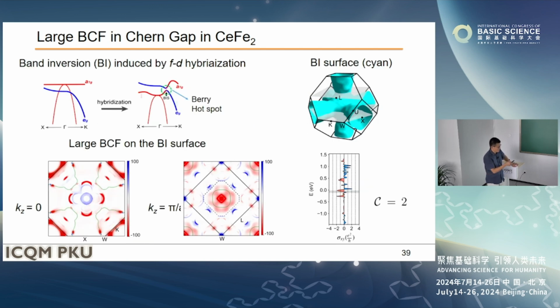How to understand it? So through the calculation, after the hybridization, you see this flat band hybridized with the f electron of cerium and open a small gap. This gap is a very strong curvature hotspot, and following the calculation, you see this gap has Chern number equal to 2, and that gives you a large anomalous Hall conductivity for this compound.